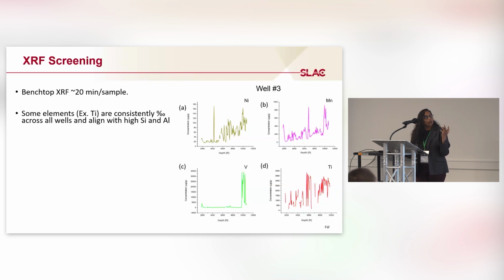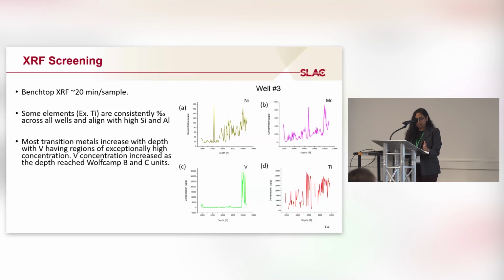And other transition metals like vanadium were seen to be present in exceptionally high concentration in most of the wells, and very high concentration in one of the wells. If you see the plot for vanadium, you can see that it skyrockets to about weight percentage level of vanadium after it hits the 10,000 feet level. And after this, an arbitrary limit of 100 ppm was chosen for the rest of the synchrotron analysis.